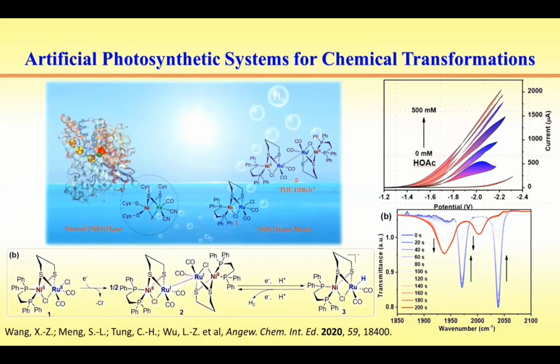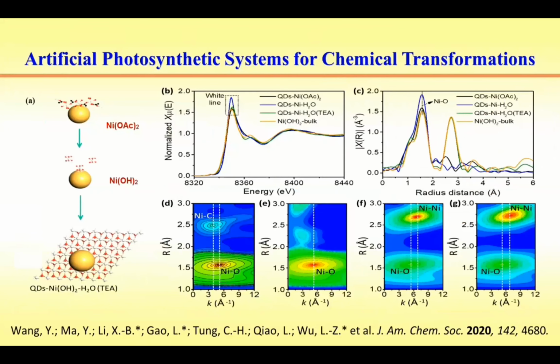The isolated dimer shows the real catalyst role for hydrogen generation, while the mimic worked as a pre-catalyst and was involved in hydrogen evolution only after being reduced to 2. The remarkable activities and catalytic reactions of this dimer structure of 2 operated in the photocatalysis. On the other hand, semiconductor quantum dots in conjunction with Earth-abundant metal ions to generate an in situ catalyst are so effective. The exact structural changes of this active site at realistic conditions stimulated us to give